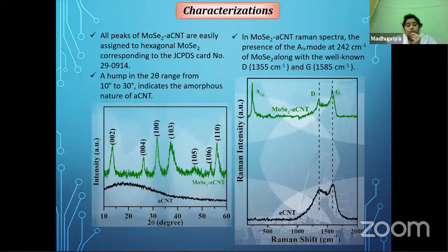Here we have shown the XRD pattern of both synthesized materials. The hump between 10 and 30 degree 2 theta corresponds to the amorphous nature of the amorphous carbon nanotube, and the other indexed peaks correspond to the proper formation of MoSe2 nanoflakes, which exactly match JCPDS card number 290914, the hexagonal phase of MoSe2. The corresponding Raman spectra show the standard D and G bands proclaiming the formation of carbon nanotube, and for the heterostructure the A1g peak at 242 centimeter inverse corresponds to the formation of MoSe2.